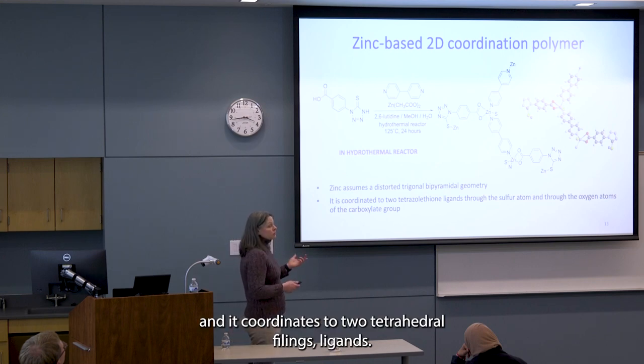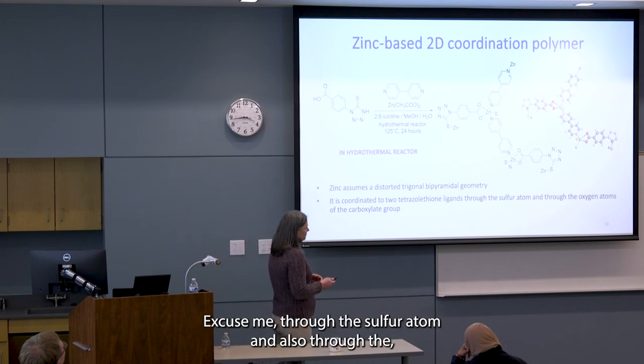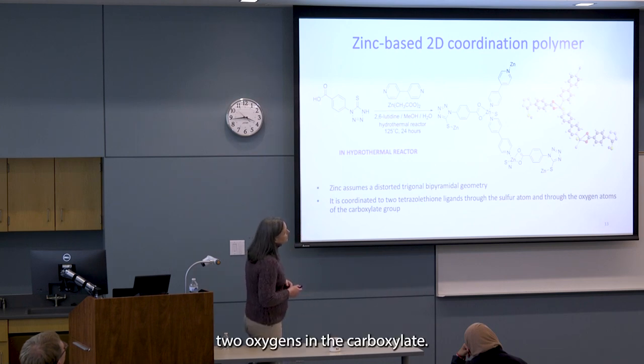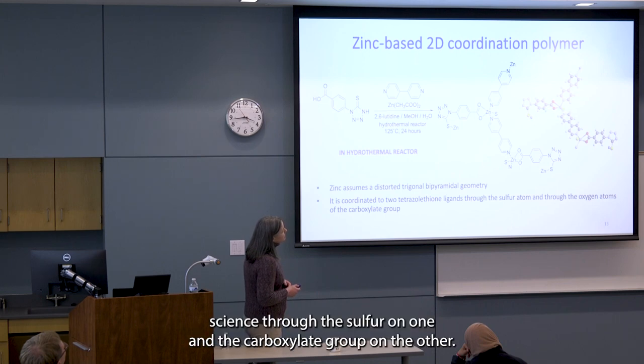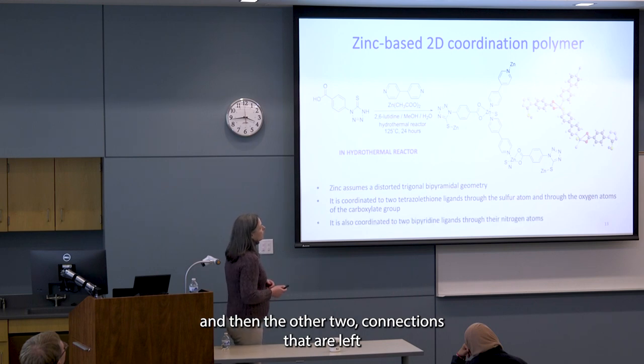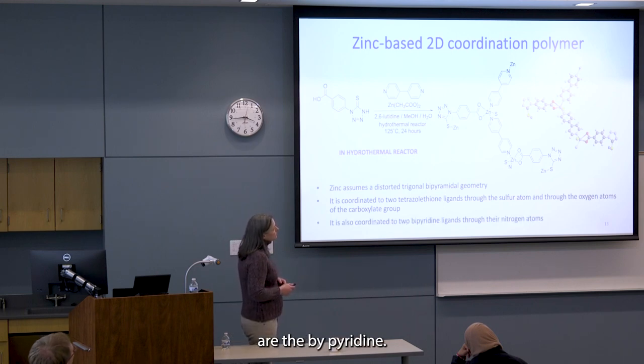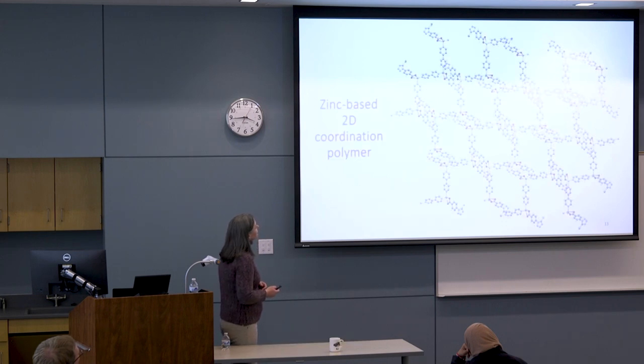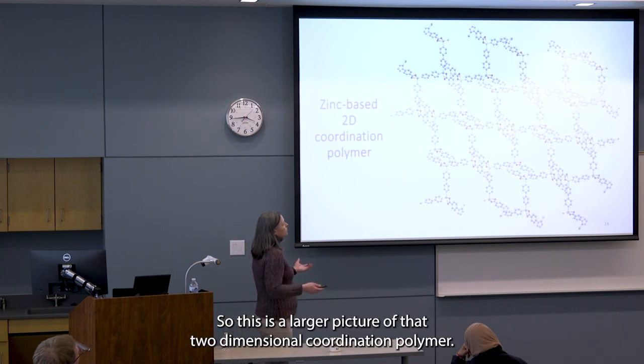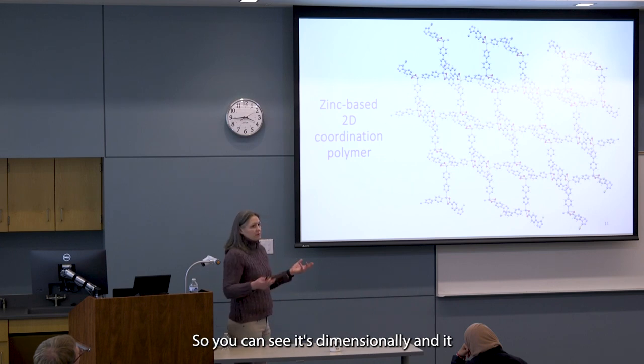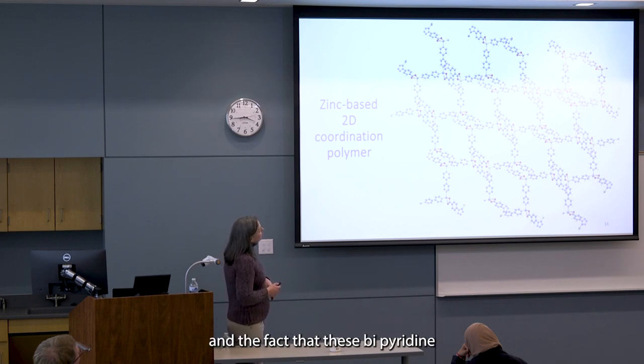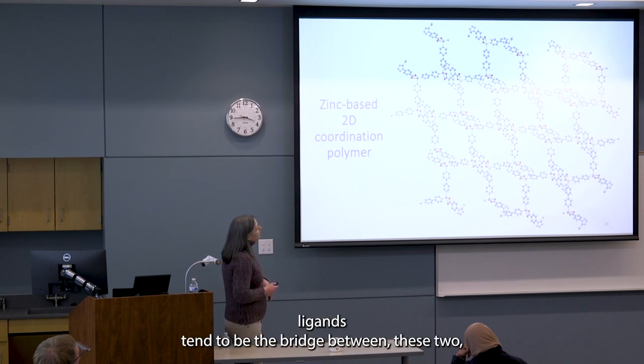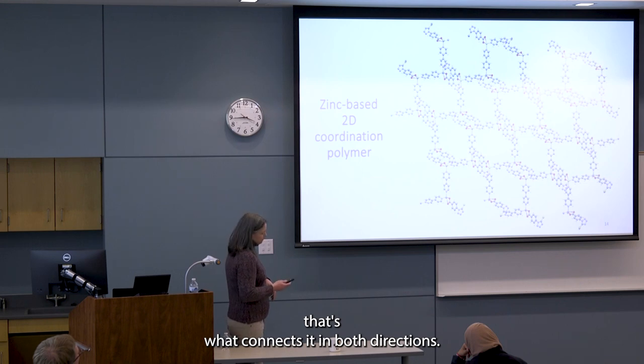It coordinates to two tetrazole thione ligands, through the sulfur atom and also through the two oxygens in the carboxylate. So you connect to your tetrazole thiones through the sulfur on one and the carboxylate group on the other. And then the other two connections that are left are the bipyridine. So this is a larger picture of that two-dimensional coordination polymer, so you can see its dimensionality, and the fact that these bipyridine ligands tend to be the bridge between these, so that's what connects it in both directions.